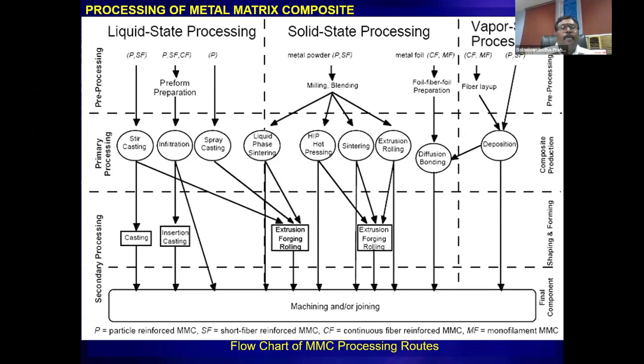And in the infiltration process, the preform will be prepared either out of a continuous fiber or a short fiber. And by infiltration, like gravitational infiltration or pressure assisted infiltration, you try to infiltrate the liquid metal, and finally you end up with the composite. In spray casting, you spray the liquid metal over the reinforcement layer by layer, and then try to consolidate.